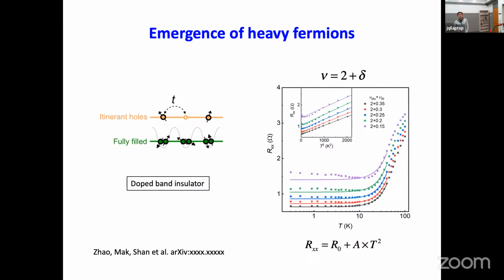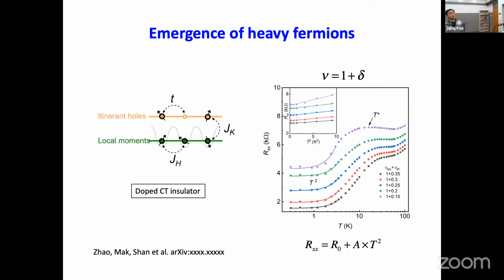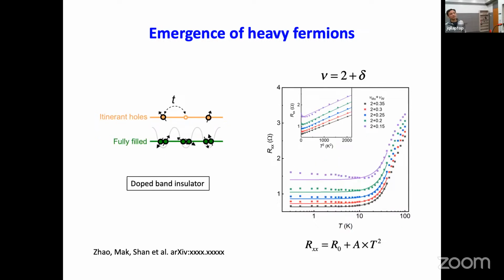This is at 2 plus delta. No Kondo physics should be there because there are 2 electrons per Moiré unit cell in the MoTe. You can still see coherent transport at low temperature, typical of a Fermi liquid, but you don't really see the presence of a Kondo temperature, no characteristic peak temperature in the system, compared to filling factor equal to 1. In fact, the resistivity will sort of saturate when the temperature becomes comparable to the Fermi energy in the system.